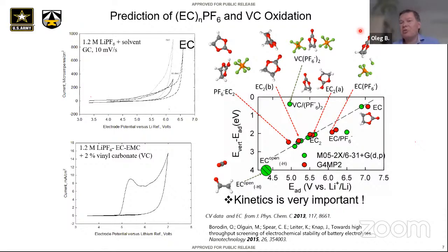I think so. That's why we wrote a paper towards high throughput screening, highlighting these two mechanisms, because in a screening you would get that VC is about 2 volts less stable than EC, and in reality it is about the same stability, but kinetics is 2 or 3 orders of magnitude higher, right? So kinetics should be incorporated. And unfortunately, this type of calculation is less suitable for high throughput.